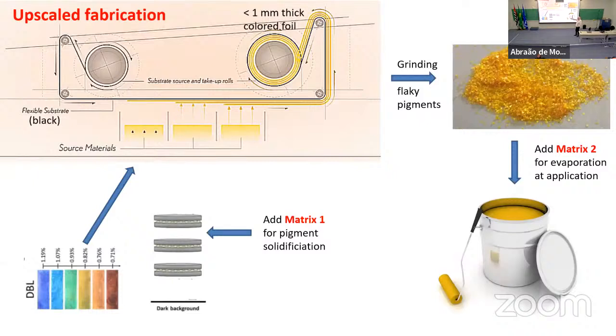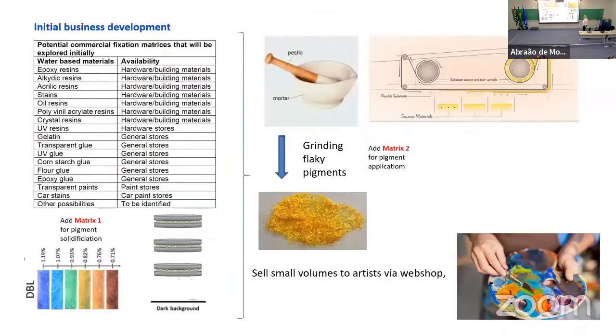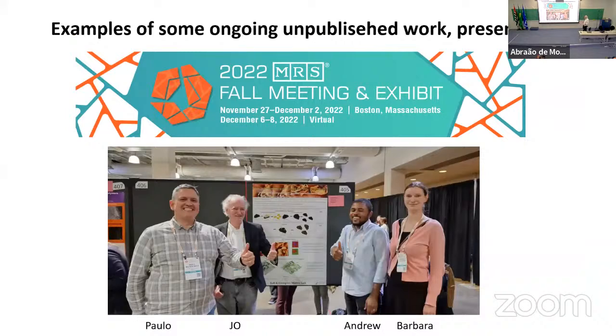So we imagine making some foil where there is not water in between the platelets, but some transparent solid matrix of some sort. We grind that foil into flaky pigments and we put those pigments in another matrix that evaporates and we paint it on the wall. That is the future of this.